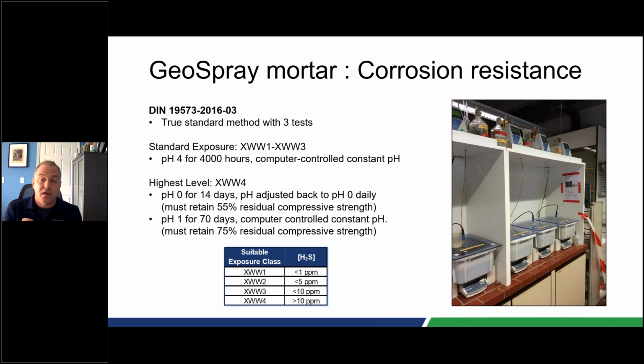The highest level is XWW4. They do 2 tests there. They do a pH 0 test for 14 days, and they want you to maintain 55% residual compressive strength. And they do a pH 1 test for 70 days. Again, the pH 0 is adjusted back every day to the original strength with an excess of acid. They would adjust it. The pH of 1 is computer controlled, so constantly adjusted. The only reason the pH 0 isn't that way is because the pH 0 eats the pH meter, so you have some limitations on the capability of controlling it.